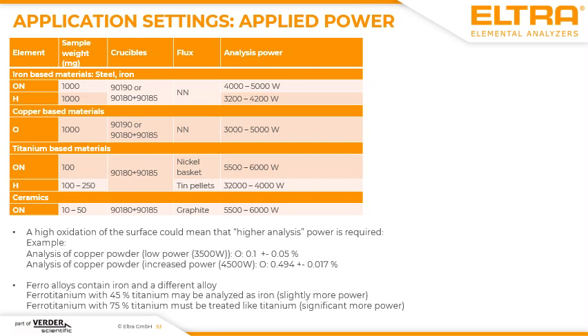This is something you also have to be aware of when you, for example, only analyze a steel sample which is present as a solid sample or as a pin. Then maybe the applied power is high enough to get a good result for this kind of solid sample. Powder could mean that you have to increase the power, maybe by about 10 or 20% for analyzing this sample. Otherwise, you may not be sure if you can crack all the bondings which are inside. So please take this as a general recommendation for analyzing unknown samples, but always be aware that with powdered samples the applied power could be much higher.